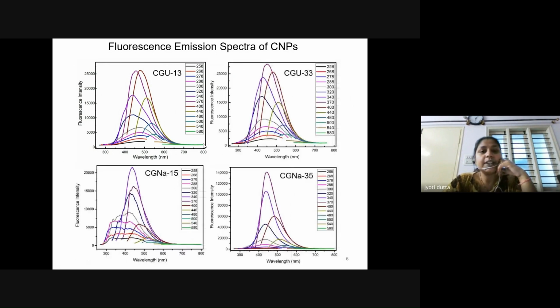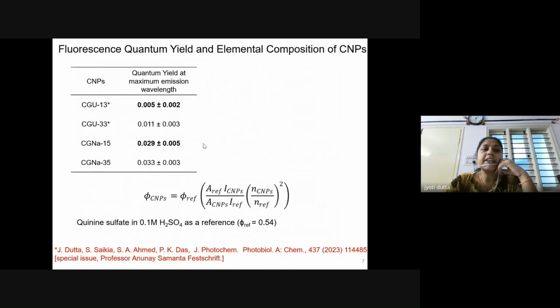Now, this kind of behavior was observed for all the four carbonaceous nanoparticles. And further, we checked their fluorescence quantum yield. So you can see the fluorescence quantum yield for the two sets of nanoparticles. All the four sizes have been shown here. We opted for the measurement of fluorescence quantum yield using a reference, which is quinine sulfate. We observed that the fluorescence quantum yield for these carbonaceous nanoparticles was not very high, it was moderate, and it was size consistent. So for larger sizes, we were getting higher quantum yield.